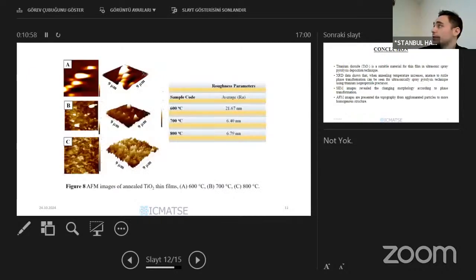These are AFM images. There are 3 images here. At 600 degrees, there are many agglomerated points on the surface. There is also a homogeneous structure, but generally we see large agglomerates on the surface. As the annealing temperature increases, our surface becomes much more homogeneous. You can see the difference between 800 and 600.